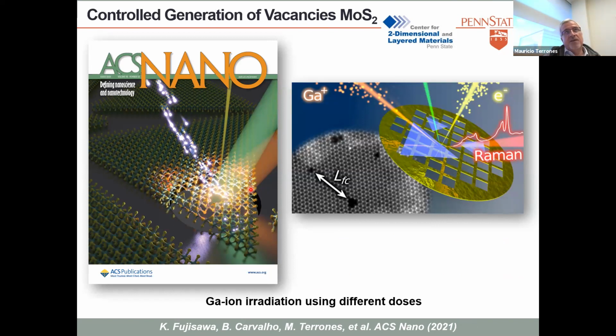Now, can we use Raman spectroscopy as a tool to estimate the number of vacancies, or the proximity of these vacancies, or how defective your material is? This is something that we did in ACS Nano. We published this recently. We used gallium ions and irradiated with different doses, and then performed Raman spectroscopy. What we calculated is the average crystalline length from defect to defect, and you can estimate this finite crystal length using Raman.